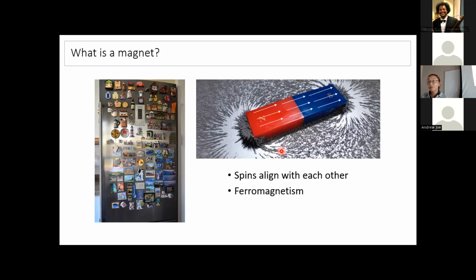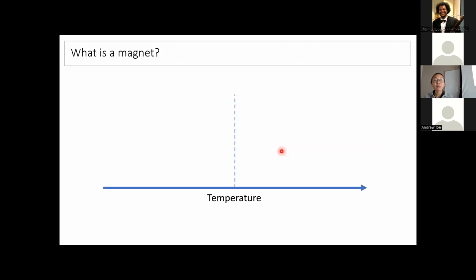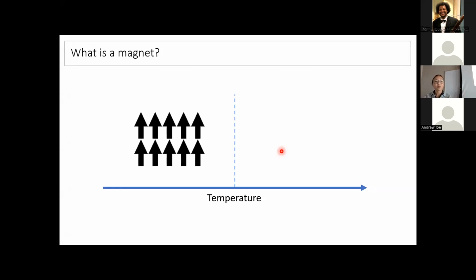And this is what's called ferromagnetism. So we have ferro being like iron. It's magnetic behavior, like what we see in iron. Okay, and something that I want to mention here is that as far as I'm aware, there are no ferromagnets that are always ferromagnets. So first of all, if you get it hot enough, it'll melt. But even before that, you'll actually stop seeing this behavior where all the spins are pointing in the same direction, and you start to get the temperature winning. So below a certain temperature, we have all our spins pointing in the same direction. Above a certain temperature, they're fluctuating, pointing in what seem to be random directions, although there's actually some information we can get about our material and what's going on microscopically, even from those random movements.